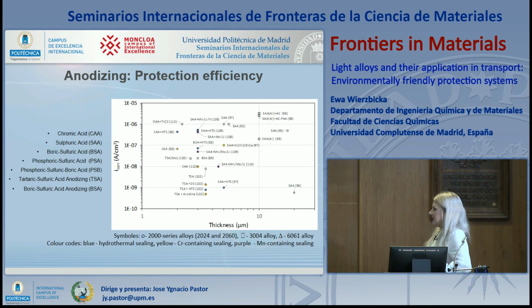To summarize, by application of varied acids for anodizing, varied modification of this procedure, like using in situ modification and post-treatments, we can obtain coatings with different protection efficiency. The good news is that by only obtaining slightly thicker coatings like those ones, we can get better corrosion protection than has the chromic acid anodizing.